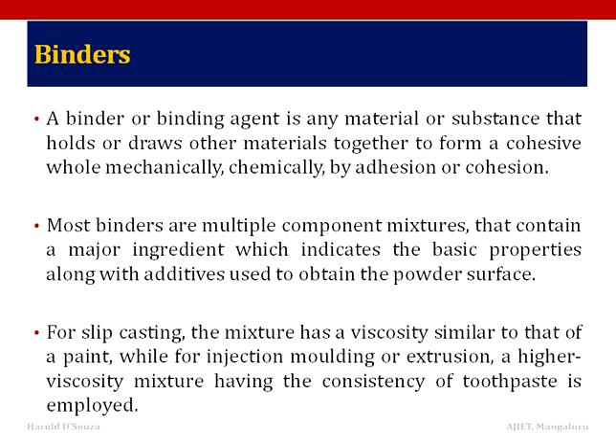After molding, the wax can be extracted by slow heating, immersion in solvents, or evaporation by heating in vacuum. A related group of binders with high water content and polymer forms gel on cooling and drying. The gels are derived from organic materials like soap, sugar. After evaporation of the water, the remaining gel holds the particle in place until sintering. Now, these are preferred for extrusion, tape casting, and slip casting.